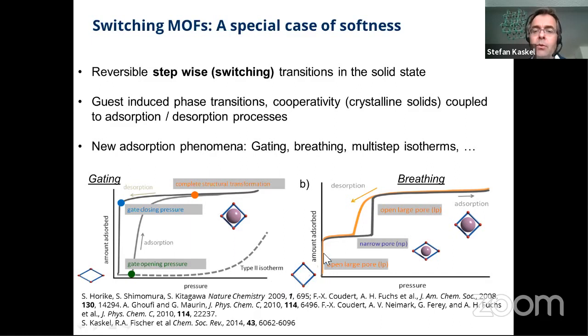But once we introduce the guest, the network starts to shrink and it shows a stepwise transformation to a narrow pore form and again to an open pore form. And here the MIL series from Gérard Férey is the most prominent system showing this type of breathing behavior.